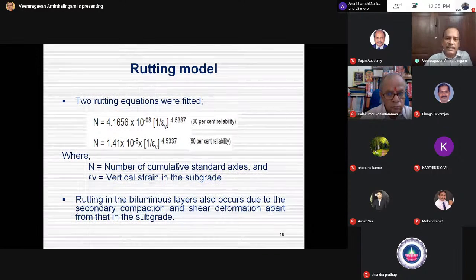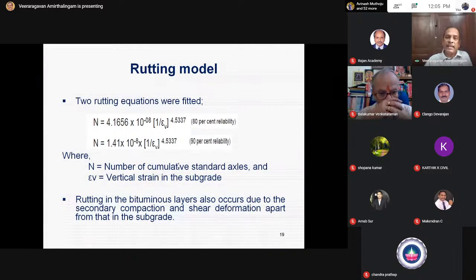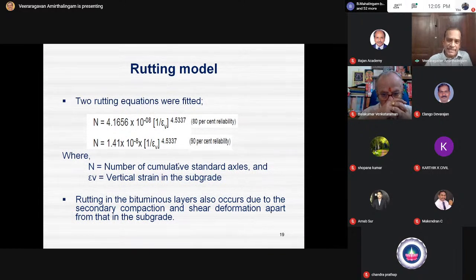But majority of the rutting that I have observed on the Indian highways, they are due to secondary compaction problem with the bituminous mix. If the gradation is wrong, binder content is wrong, or binder type is wrong, how do you account for it? That is another $1 million question. So if I use a modified binder, will it perform? May perform, but again, we need a different fatigue model.